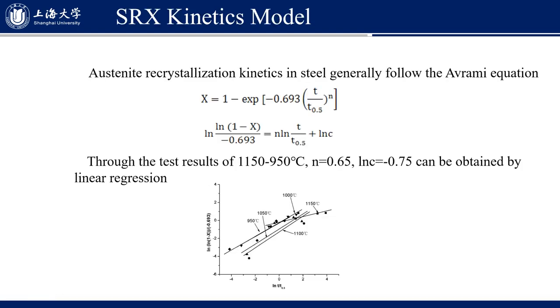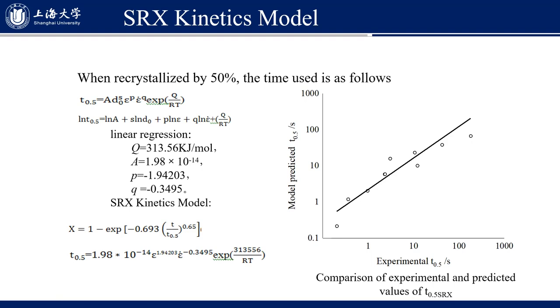From the above study, the static recrystallization kinetics model is established. Austenite recrystallization kinetics in steel generally follow the Avrami equation as shown here. Through the test results at 1150 and 950 degrees C, the n value and C value are obtained by linear regression. When recrystallized by 50%, the time used is as follows.